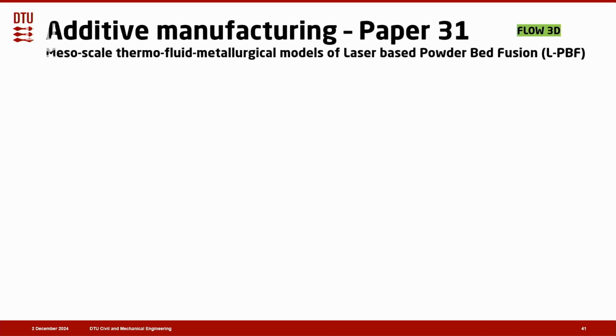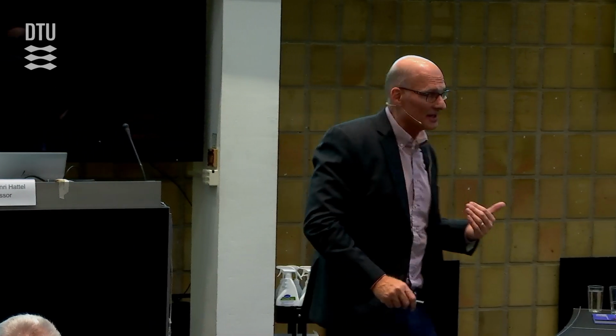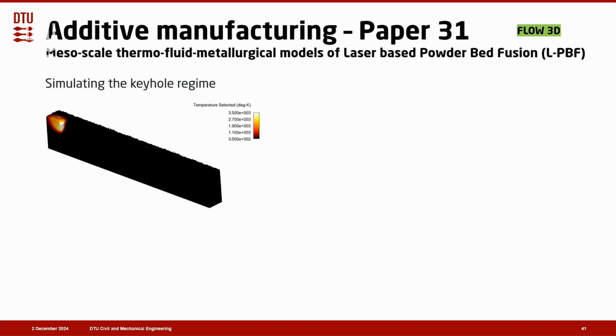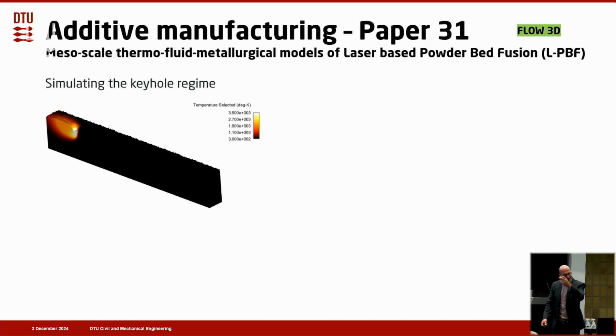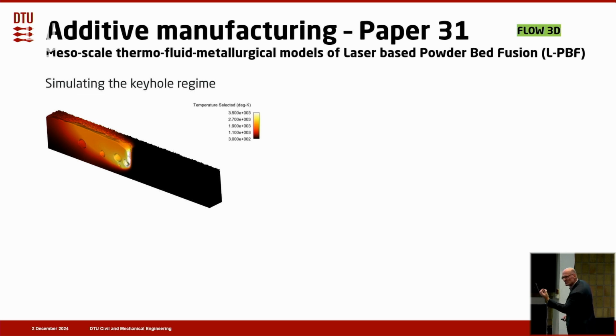Then we proceeded with a mesoscale thermofluid metallurgical model. Again, it was actually the one from before, but we used it in another case where the energy intensity is higher. So this is where you get the keyhole regime. Now, a keyhole is a very unstable situation. It sometimes snaps off and then becomes a bubble.